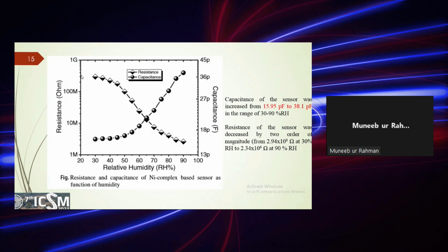Similarly, due to the hydrogen transfer, the protonic conduction or H+ ion transfer, the resistance of the sensor material is decreased from 2.94 × 10^8 ohm at 30% RH to 2.3 × 10^6 ohm at 90% RH. So when we increase the humidity from 30% to 90% RH, there is a drop of 2 orders of magnitude in the resistance of the sensor.